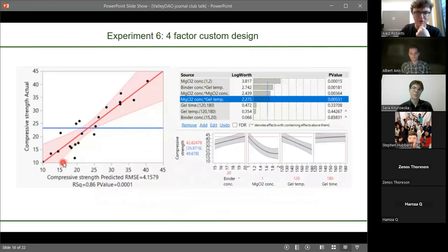Then we did one final custom design just to try and push the compressive strength even further. But essentially what we found was that if we increased the magnesium chloride concentration even more, it went down. If we increased the temperature even more, and now we could do that because we weren't using urea anymore, so there was no poison gas being produced, it actually made the samples worse, less strong. So it suggested we'd already found the peak of that complex experimental space, and pushing the factors to even more extremes didn't help. We were at that peak of the hill.